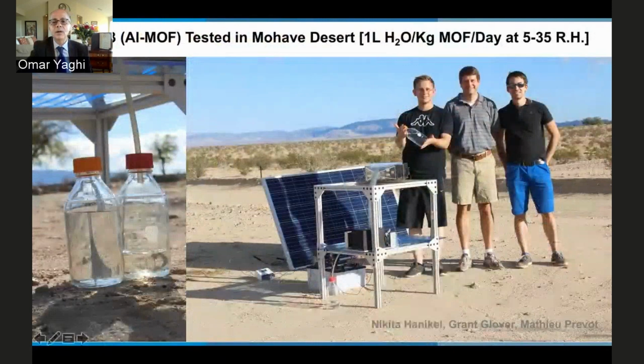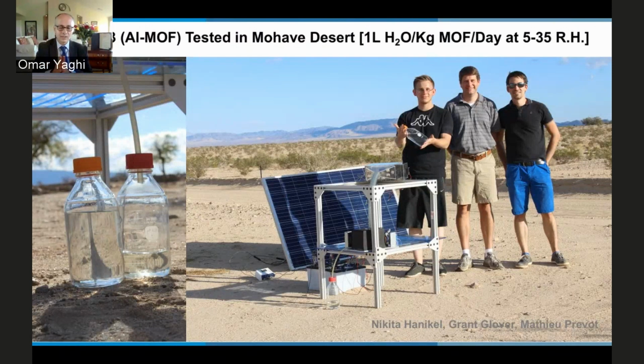You can see here, the students came back with this video showing dripping of water as the device is cycling through, taking up water from air and using the power, heating up the MOF to release the water and then condense it. So from that experiment, we harvested 1 liter of water per kilogram of MOF per day. That's using a little bit more of the MOF. Still, we're not using the entire MOF material. I just want to emphasize, this is a kilogram that now has been tested over 30,000 cycles. So it stays in the device for the lifetime of the electronics, around 5 to 6 years, delivering 1 liter of water per kilogram of MOF at very low humidity range.